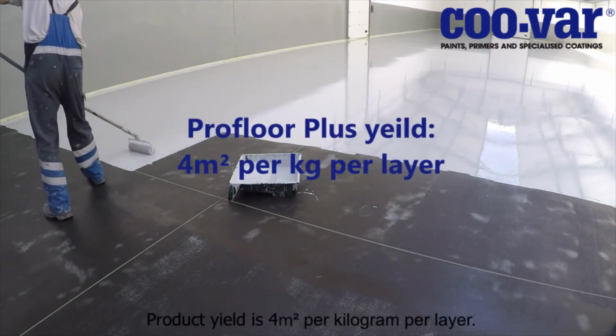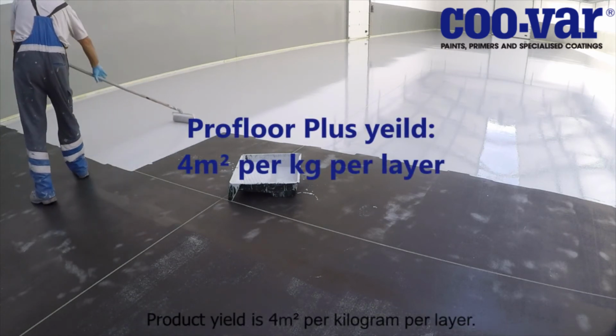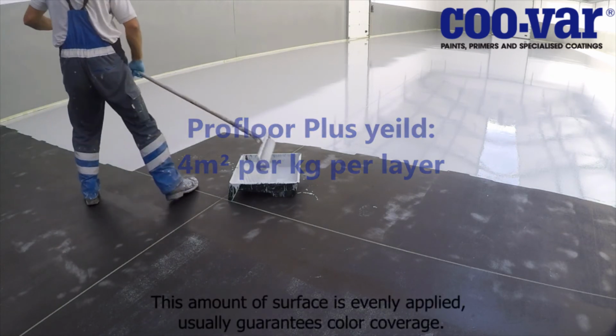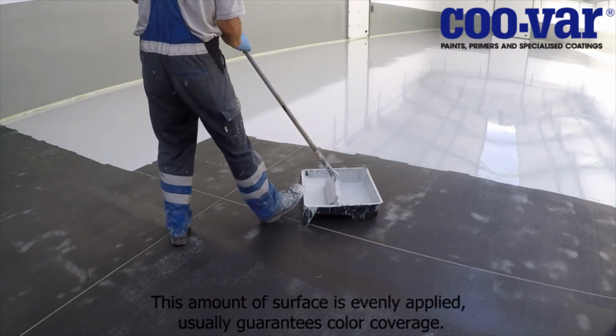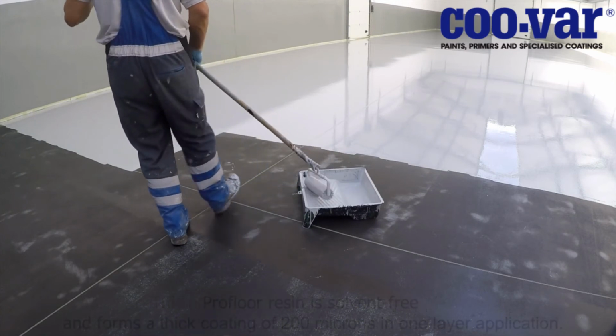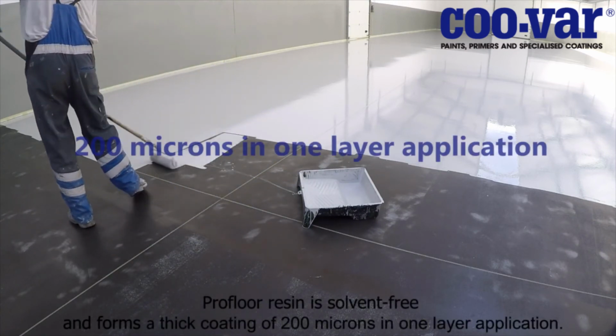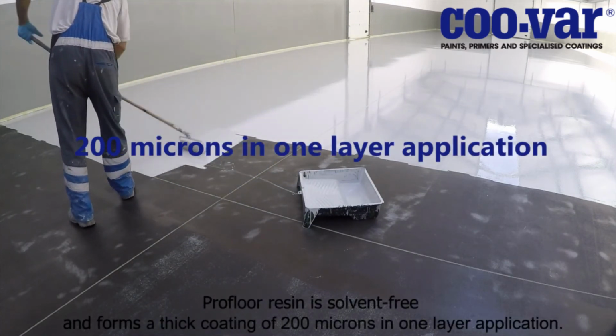Product yield is 4 square meters per kilogram per layer. This amount of surface, evenly applied, usually guarantees color coverage. Profloor resin is solvent-free and forms a thick coating of 200 microns in one layer application.